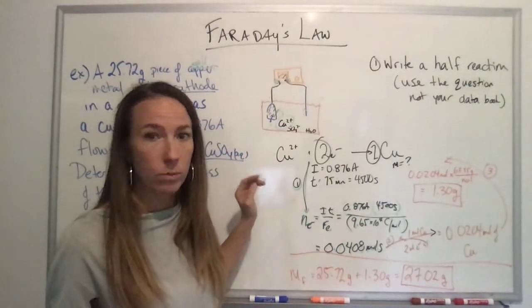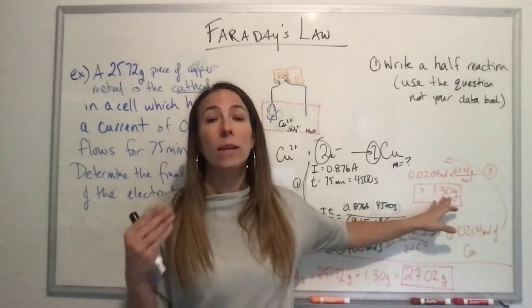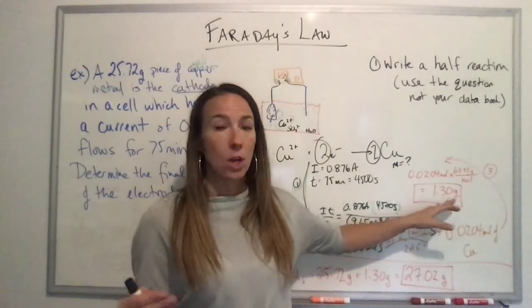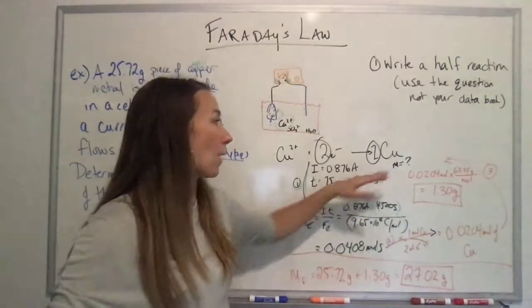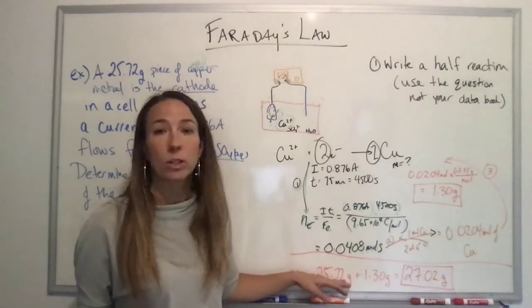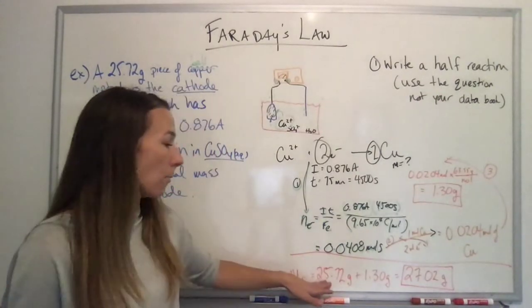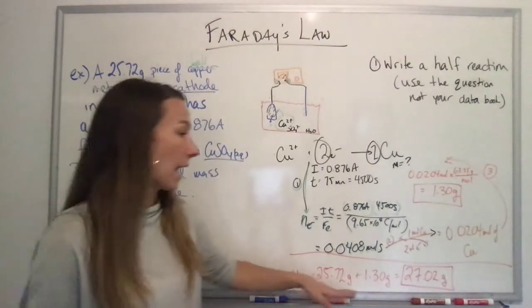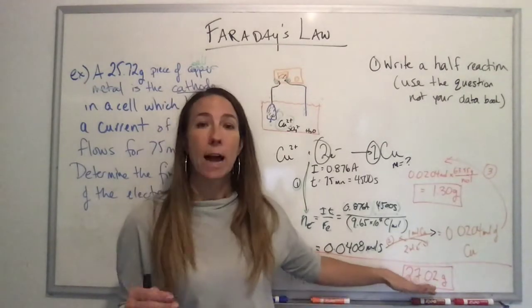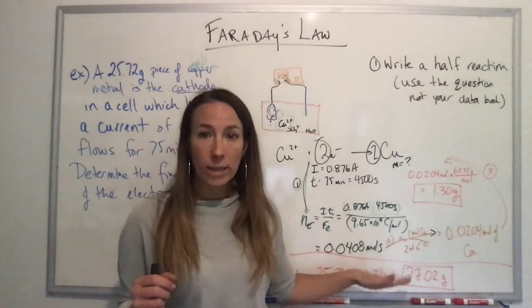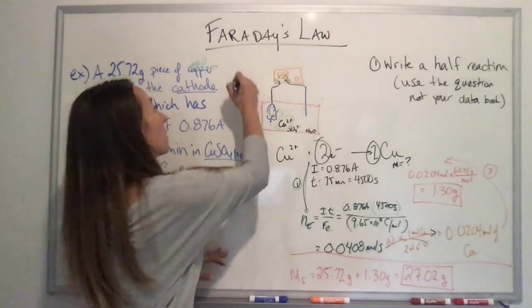The second part of my stoichiometry dance is to multiply that. I have to change the subject from electrons into copper and the only thing that can do that is my balanced chemical equation. So one mole of copper over two moles of electrons, so I'm timesing that by one and then dividing it by two to get my moles of copper which is 0.02. If I have 0.02 moles of copper, can I figure out the mass? Sure, I'm just going to use the molar mass. The moles of copper times my molar mass is going to give me my mass of copper. So if I turn this battery on for 75 minutes and I make sure the amperage is 0.876 amps, I'm going to make 1.30 grams. That's my 1.30 grams that I'm creating and then I'm going to add that mass to the original mass of the bell because it's going to stick to the bell. I add the 1.30 grams to it and my final mass of that bell is going to be 27.02 grams. This is also called electroplating.